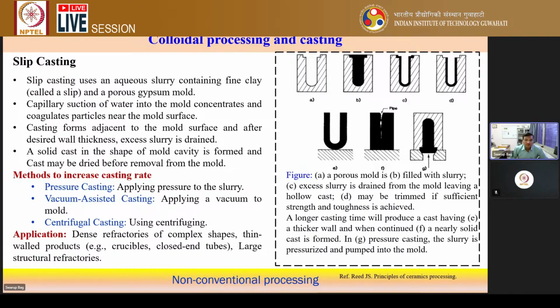This is the way we follow the slip casting process, and the deposition of the clay over the porous medium, the gypsum mold, can be accelerated in different ways. You can perform pressure casting, vacuum assisted casting, or centrifugal casting. In pressure casting, we apply some pressure to the slurry so that deposition can be accelerated. Vacuum is the same: apply vacuum to the mold, create a pressure difference, and that helps increase the deposition rate. And in centrifugal casting, you simply use a centrifuging mechanism to deposit the material over the porous mold.